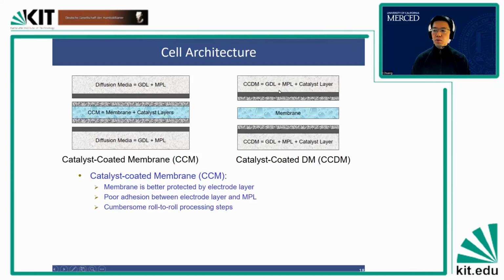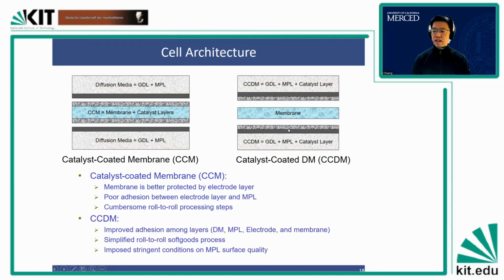So later on, we developed this cell architecture where you have the membrane, but the catalyst layer is coated directly on the GDL and the microporous layer. The advantage is that it improves adhesion. Later on, this goes through hot press, so it becomes a multiple layer structure in very intimate contact. This process also has the advantage of simplified roll-to-roll processing steps for manufacturing. So this was my last project before I left General Motors.